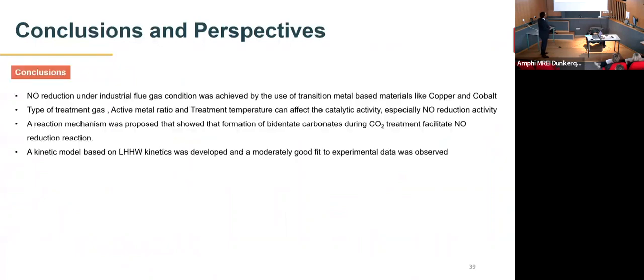Finally, we come to the end of our presentation. So some of the concluding remarks, we saw that the NO reduction by CO is possible under the industrial flue gas conditions using transition metal based materials, generally copper and cobalt as the active metals. We used a material development strategy where we use type of treatment gas, active metal ratio, and treatment temperature as the parameters to optimize our catalytic material suitable for the NO reduction reaction.